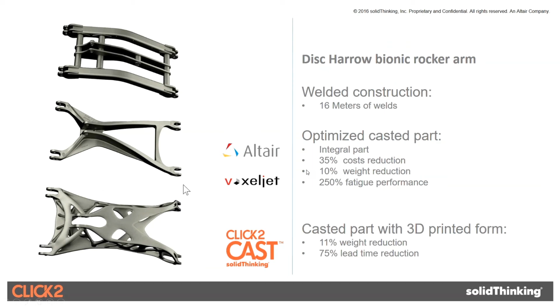And in addition, the weight was 11% less, and also 75% lead time reduction, because you're reducing the entire tooling time by printing the entire tooling in one shot. So there's a tremendous amount of savings in this particular approach.